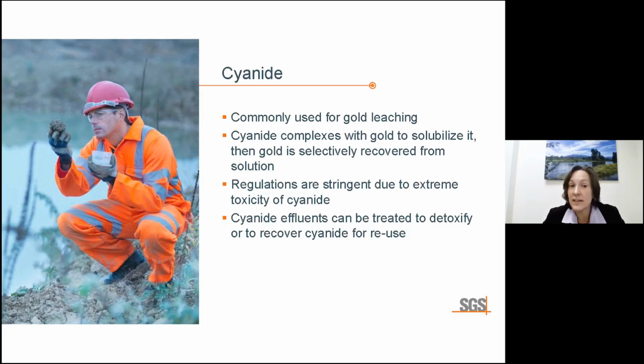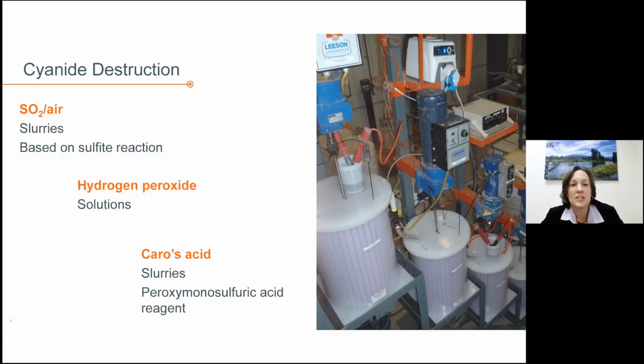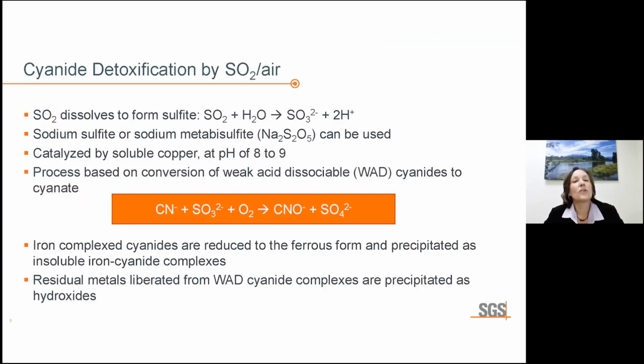We can also recover the cyanide for reuse. When we look at cyanide destruction, there are three common methods used in gold mining. The SO2 air method is used mainly for slurries, and it is based on a sulfite reaction. Hydrogen peroxide is used for solutions, and Caro's acid, the common name for peroxymonosulfuric acid, is also used for slurries. Looking at the SO2 air process, what we're really working with here is the sulfite reagent.